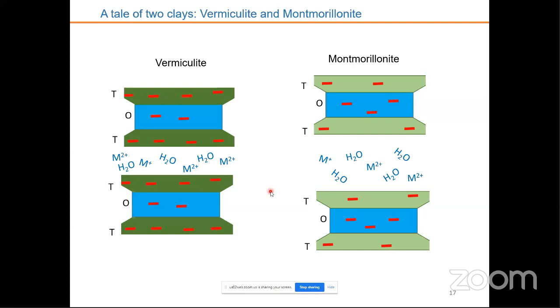In the second case, we have taken two clays. One is vermiculite, one is montmorillonite. Both of them are 2:1 clays. 2:1 clay means we have one octahedral sheet between two tetrahedral sheets. Both have a similar structure. The slight difference is that in vermiculite, most of the charges are in the outer layers. So we have negative charge in the outer layer, which attracts the cations present in the channels, so they are strongly held. It will not expand very easily.